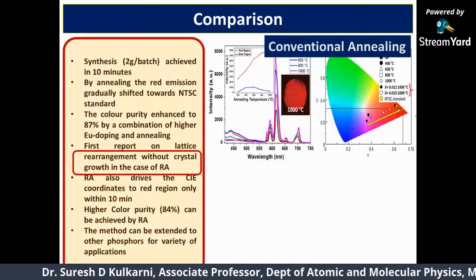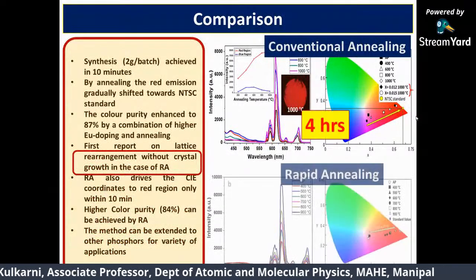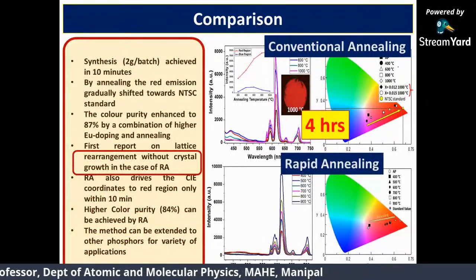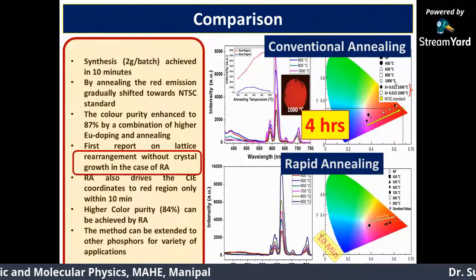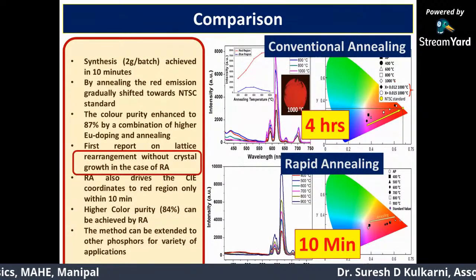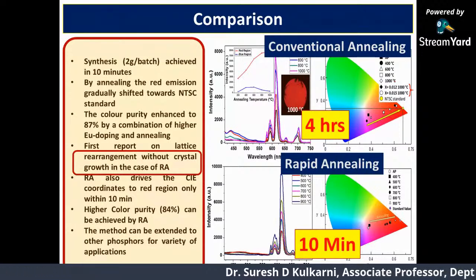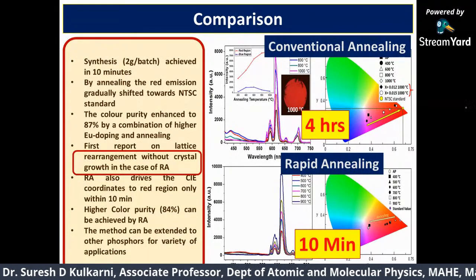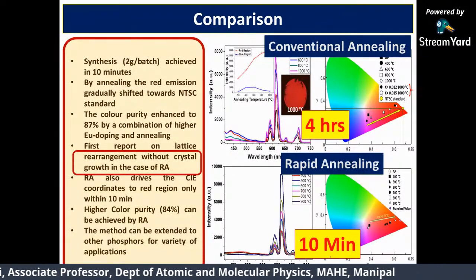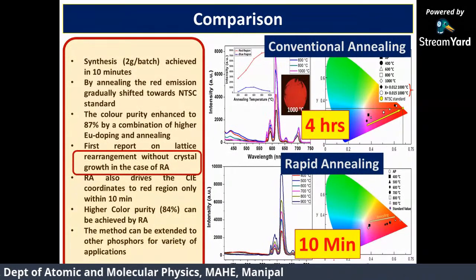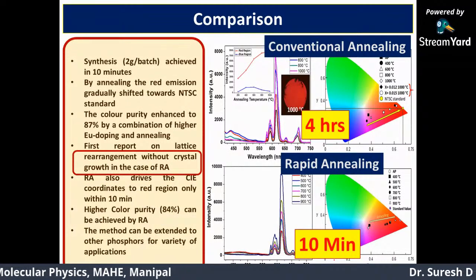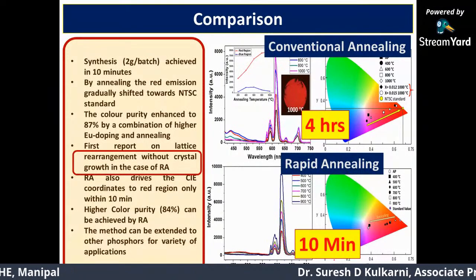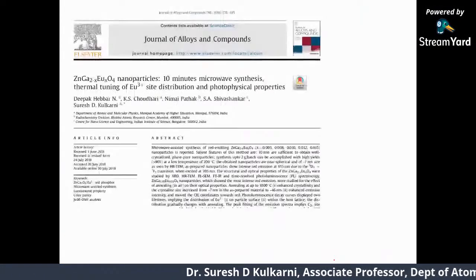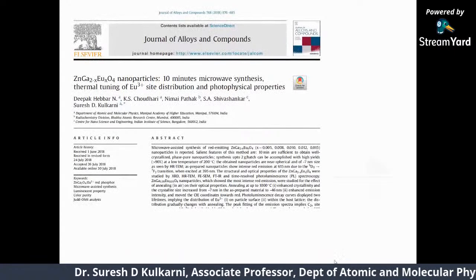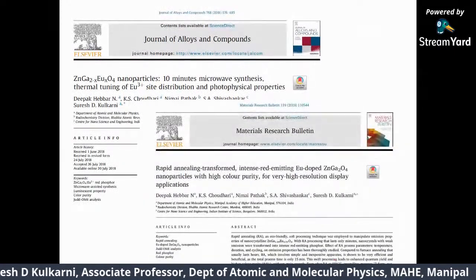The comparison of the optical property I am showing here. The conventional furnace annealing of the same material takes about 4 hours. Okay, and when I say 4 hours, actually I can take out the material only the next day because the furnace will be quite hot. Whereas in the rapid annealing process, you can take out the material in 10 minutes after the process. Within 10 minutes, you have the material in your hand with very good color output. Okay, the details can be found in our publications. Couple of publications are there.